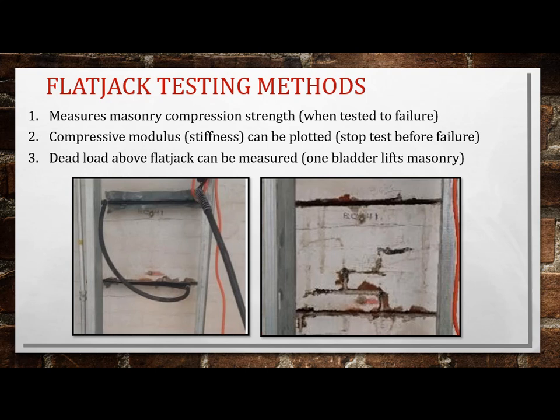The third one is actually to use a single jack, single bladder. So you grind out one mortar joint, you insert your flat jack, and then you put a gauge point above and below, and so you start pumping it up, and so it spreads out, and you actually lift the wall up above. And so when that bed joint opens up, you stop the test, and then you bring it back down. But you can actually measure the amount of axial force in that area of the wall.